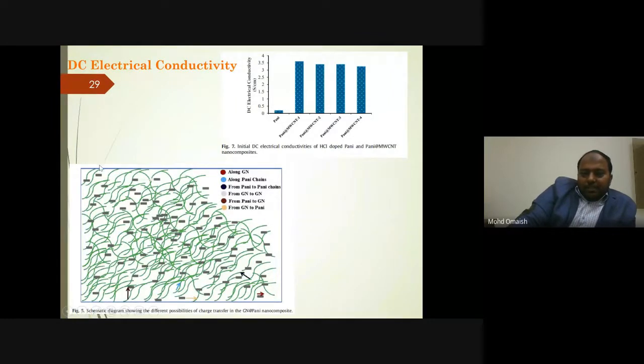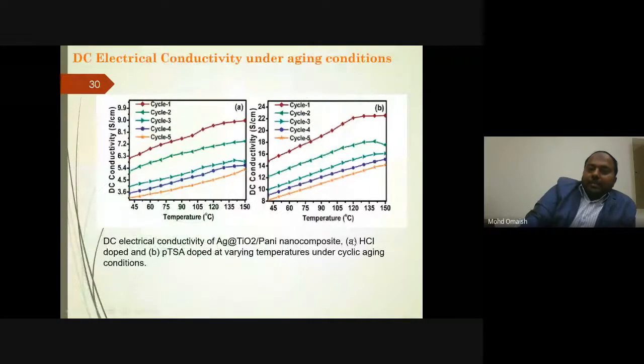And this figure shows different types of charge transfer in conductive composites. For example, in this case of polyaniline graphene, it can be along graphene, along the polyaniline chain, or from polyaniline chain to polyaniline chain. That is the charge transfer of electrons from graphene to graphene, from polyaniline to graphene, and from graphene to polyaniline.